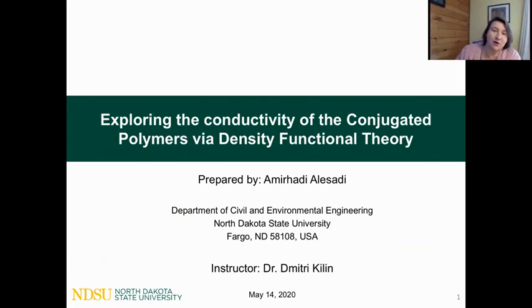If you take an ideal polymer, or maybe not a polymer, let's talk about inorganic material, a semiconducting metallic lattice with a very nice lattice structure, what do you expect to see in your radial distribution function, and how will it be different from the amorphous case, where the lattice does not have exactly the same structure? I believe in an ordered structure, the RDF peaks will be narrower and more concentrated. But for the amorphous part, there will probably be multiple peaks, and the fluctuation makes it hard to distinguish. That's my opinion.